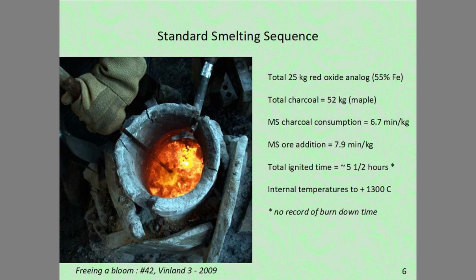The smelt would use a fairly standard operating sequence. We would add a total of 25 kilograms of red oxide analog that was developed here. The main sequence charcoal consumption would be 6.7 minutes for each kilogram. The main sequence ore addition would be 7.9 minutes for each kilogram. The total ignited time for the furnace was approximately 5.5 hours. We would expect internal temperatures to exceed 1300 degrees Celsius.